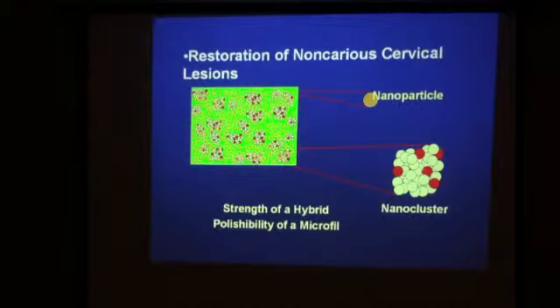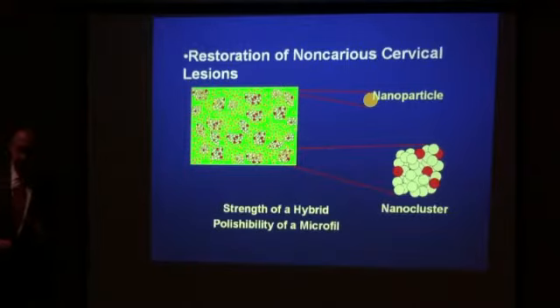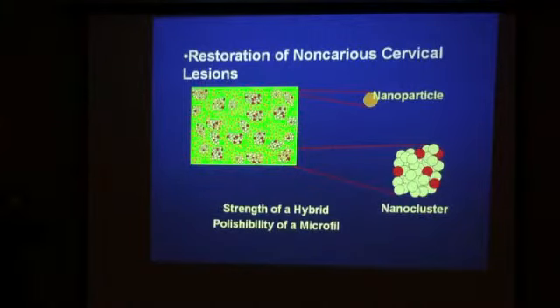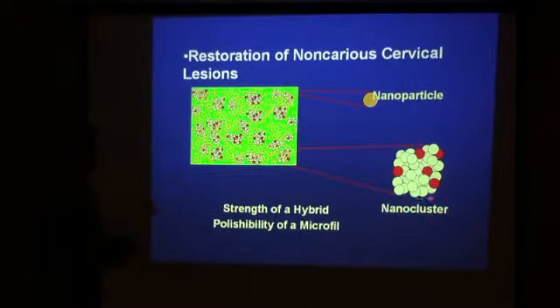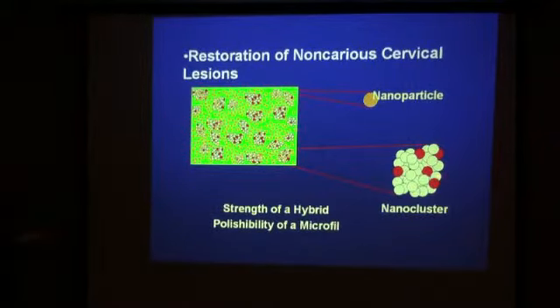What's exciting about these products is the technology of the filler particles, because these are very small particles. They're actually made of zirconia, which is a very hard, very durable material. But what's interesting about 3M's technology is they can sinter these particles into very small sizes, and then they can fuse them into clusters. So we've got these fused particles forming a nano cluster. What this does is it gives the material the strength of a hybrid from the nano cluster, and it gives the material the polishability of a microfill resin because of the nanoparticle.